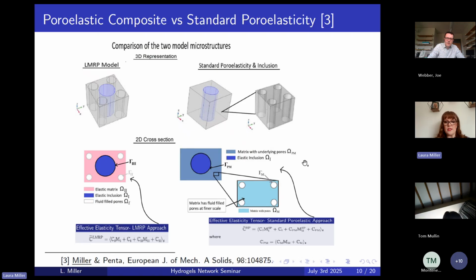So here, just to explain a little bit about what we need to compute, I've got my very simple 2D cross sections of my material. As I mentioned here, in our material, we have solid matrix, solid inclusion, and cylindrical pores. And this was our effective elasticity tensor that we needed to compute. So that was going to be reasonably straightforward simulations to carry out. We can compute this directly by solving cell problems that we developed in our model derivation.